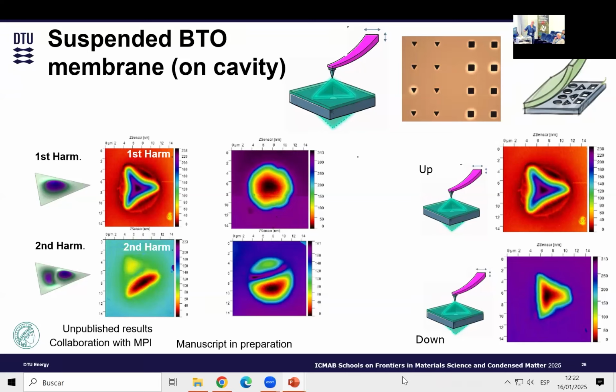oscillation in the material. So basically we observe how the material behaves, and this is due to, I mean, you get these different modes due to a few things. You get it due to the size of the pore. You get it due to the thickness of the layer that you use, and the compressive strain that there is. So it's a combination of all of this. What we observe at different places on the membranes for certain shapes. We have seen it also for circular. We've seen it also for hexagonal. We can see all the modes, at least the first, the second, and the third mode, and we can also simulate it.